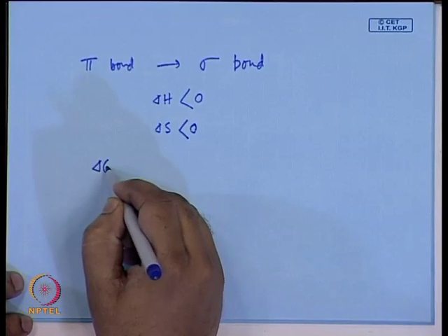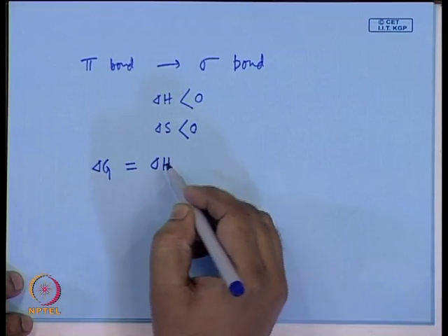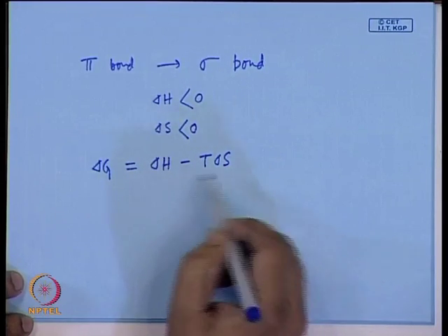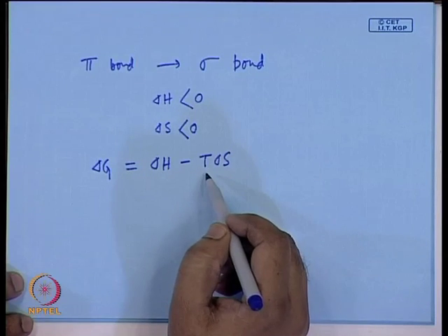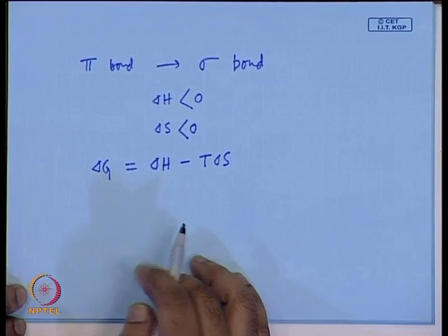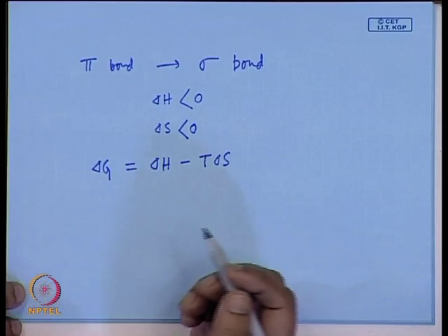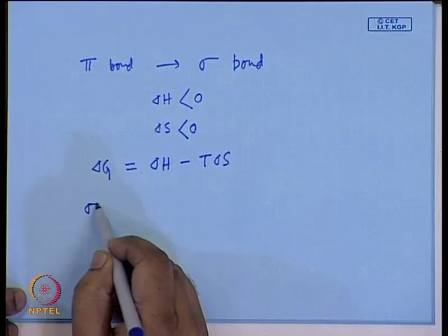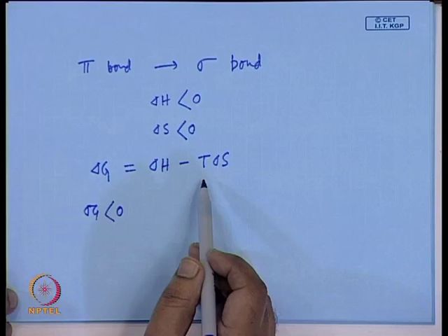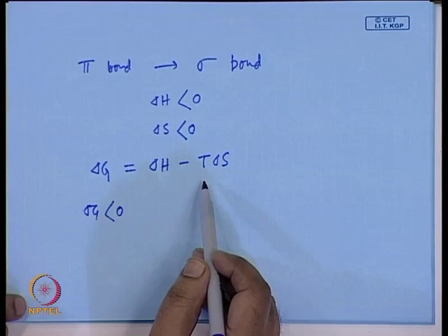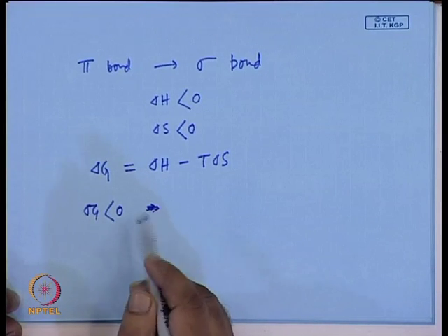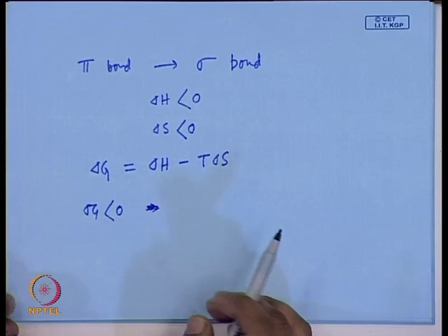So, if you think about the thermodynamics of this chain polymerization briefly, the enthalpy term is exothermic, negative, and the entropy term is also negative. So, there is a competition between these two terms. And at normal reaction temperature, the temperature where we do reactions, the enthalpy term dominates. So, chain polymerizations are thermodynamically feasible in most cases. This delta G is less than 0 for the typical temperature where we do reactions in the lab, which means that most of these double bond containing monomers should polymerize given their thermodynamic feasibility.